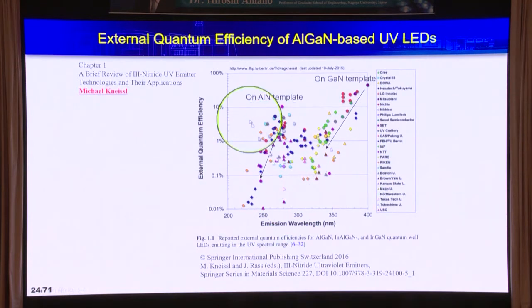This figure shows the external quantum efficiency of aluminum gallium nitride-based UV LEDs. There are two trends, gallium nitride template and aluminum nitride template. The peak efficiency is around 280 nanometers. Let me explain the details.